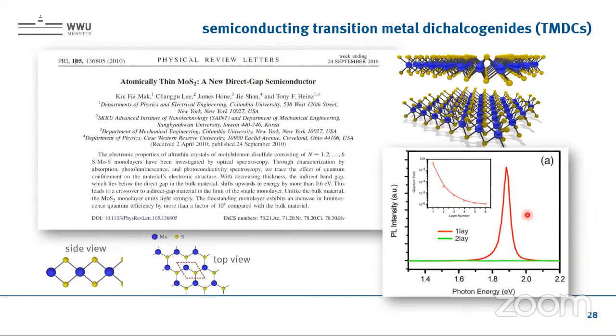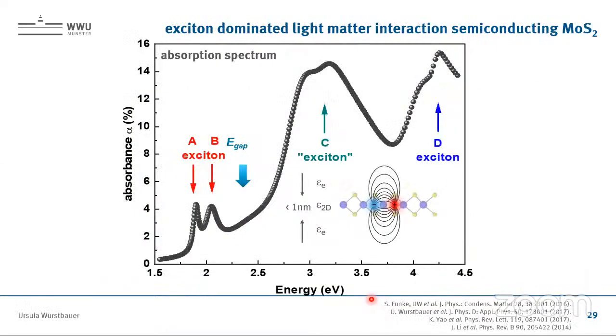And it can be explained that due to the stacking, due to the change of the number of layers, you change the properties of the material such that you change from a direct gap semiconductor to an indirect gap semiconductor, fundamentally changing the properties. It's a combination of confinement and hybridization which goes on here. So meaning we have highly tunable materials now.